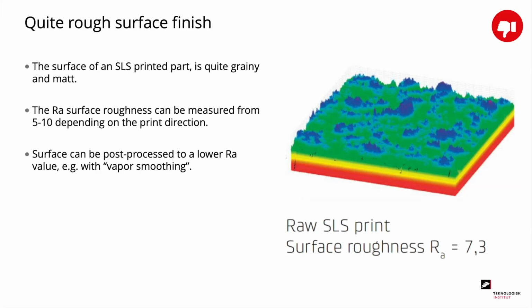One of the main drawbacks of the SLS technology is that it has quite a high surface roughness directly from the machines. Typical Ra values are between 5 and 10 micrometers, depending on how you have oriented the parts, as well as the layer thickness and some of the other build parameters. But directly from the machines, relatively high roughness. There are a number of ways you can post-process the parts to get acceptable surface roughness, depending on your requirements and your applications. For instance, we see quite high requirements in the food industry, but there is equipment that can bring you to that level of satisfaction.